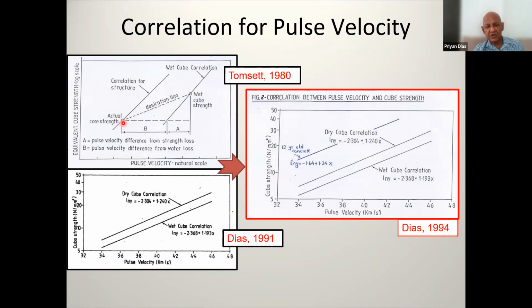In the structure also, you can get a core and do the test. And just before you do the core, you can do a pulse velocity, right? But you can see that there is a drop in pulse velocity as well as a drop in strength. Now, this drop in strength, hold on, okay, let me look at it this way. This drop in pulse velocity will occur because there is a difference between the wet cube strength and the strength in the structure. That is why, for those of you who are civil engineers, you know that when we do a grade 25 concrete or something like that, when we do the design calculations, we do not use 25 in our design calculations.